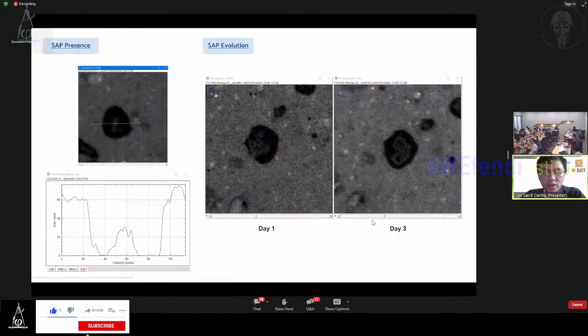To prove the presence of SAP, we can scan a specimen with SAP that has absorbed some tracer. So the SAP can be identified. From the line profile, SAP showed in the center of the pore. SAP evolution can also be observed. The SAP becomes smaller because of the release process. In summary, we can say superabsorbent polymer is effective as an internal curing medium based on compressive strength and pore properties. Thank you.